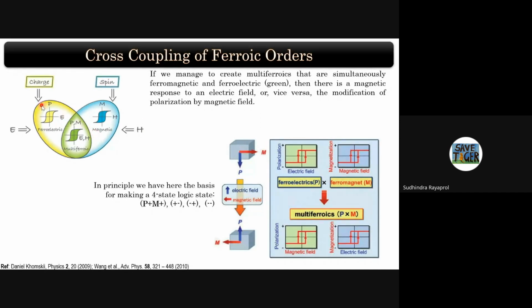What you mean by that is that if you have a ferroelectric phase and you have a magnetic phase, then by applying an electric potential you can change the magnetism, or by applying a magnetic field you can change the polarization. That will be the cross coupling which should exist in the same phase.